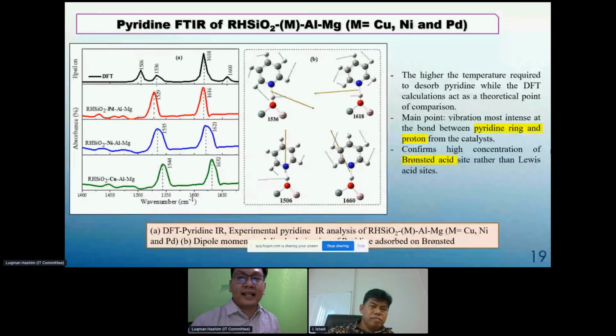The pyridine ring is actually reacting strongly with the proton from the aluminium. And we confirm that Bronsted acidity is the one that exists on our catalyst, and that's good for our esterification process. Okay, structural and morphological. We did chemical analysis just now. We are focusing on structural now.